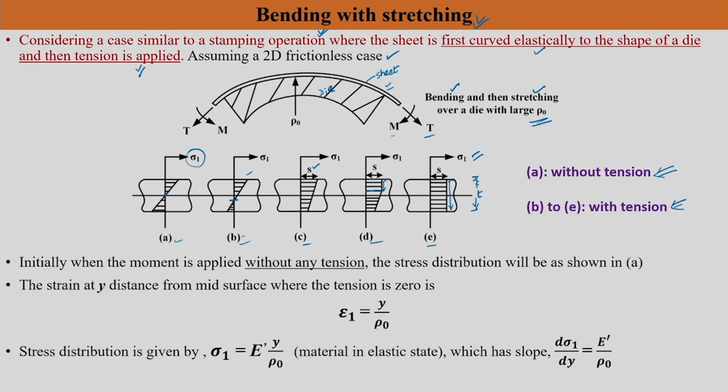Okay. So, only moment is A, you just provide some tension. B, increase the tension so that the upper surface reaches S flow stress, nothing but the yield stress. Then with further progress you will see that the S will propagate in the section, this is an elastic to plastic transition, and then here you will have a fully plastic section.